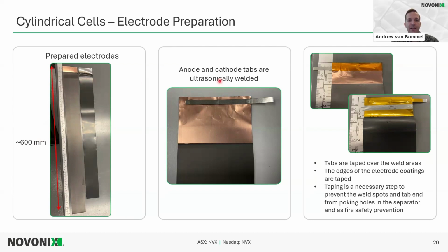The anode and cathode tabs are ultrasonically welded. Here I'm showing the anode tab, the nickel tab. Then tabs are taped over the weld areas, and those edges of the electrode coatings are also taped. This tape step is necessary to prevent both those weld spots, so you see 1, 2, 3 weld spots in the anode electrode, from poking holes in the separator. And so that's fire safety protection for the cell.